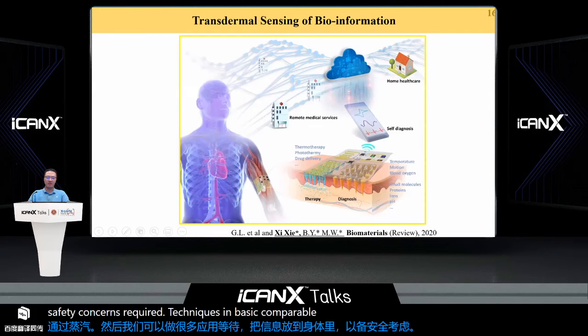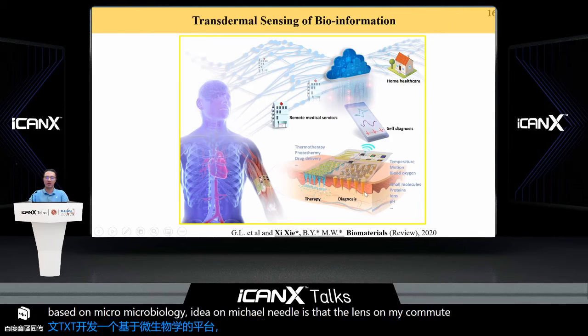So in order to penetrate skin painlessly and safely, we developed a platform based on microneedle technology. The idea of microneedle is that the length of the microneedle is in the range of 500 to 800 micrometers, which is so small that it can penetrate skin without reaching the nerves and the blood vessels in the dermis level. Therefore, it can penetrate the skin without causing pain and bleeding.